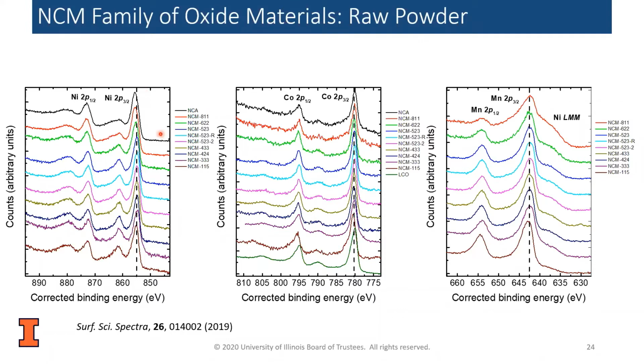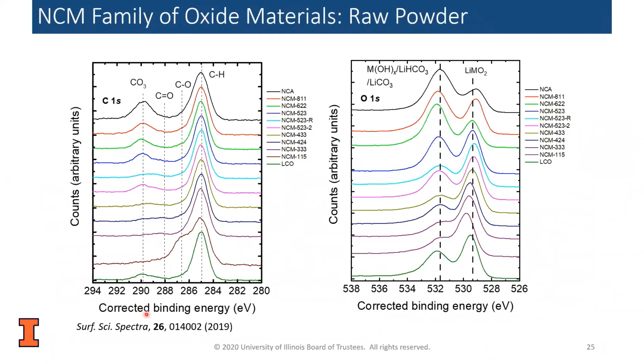If we look at the different compositions, these are the high nickel constituents, the 811, 622, and then we'll go down to the low nickel. You see the metals all pretty much look similar. Where we see a lot of difference, though, is in the chemistries of the carbon and the oxygen. Here we see in the very high nickel compositions, we have a lot of carbonate formation as compared to the lower compositions. This is also shown in the oxygen spectrum. In fact, in the highest nickel compositions, it appears that this high binding energy peak actually exceeds the intensity of the metal oxide peak right here.